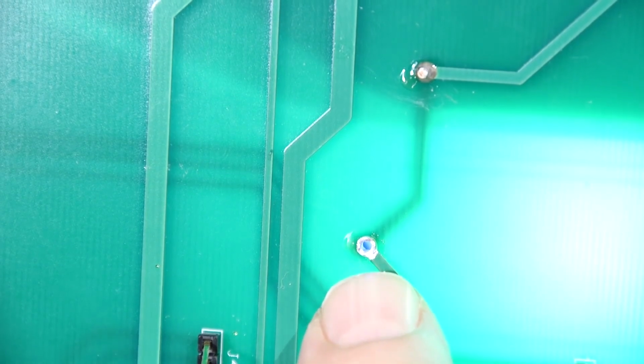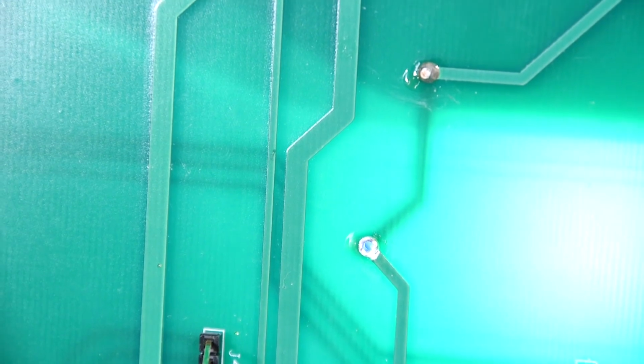Now it's quite a fine balance when you're soldering. If you have the iron on the board too long, you'll cause these things to lift off the board, and you don't want to do that. So having your soldering iron temperature right is very important. When I'm soldering these boards, my soldering iron is between 300 and 350 degrees C, and it seems to work just fine for these plated through holes.